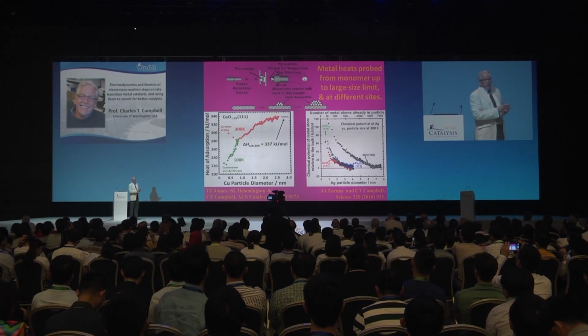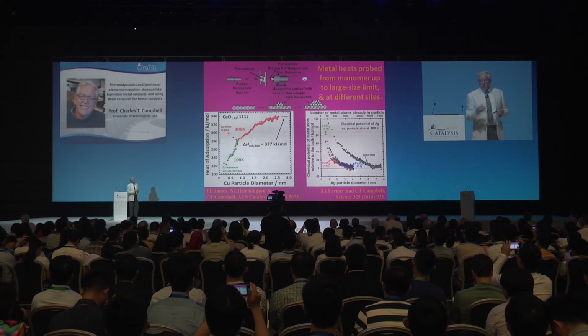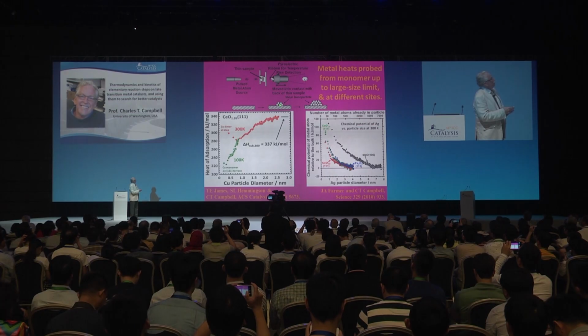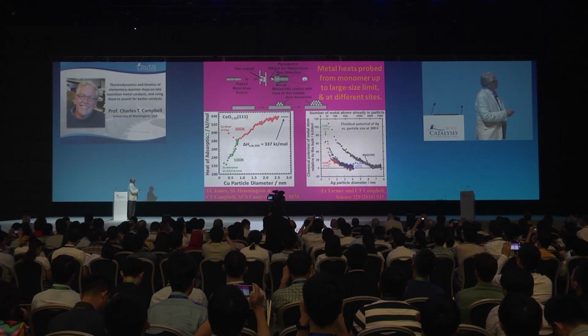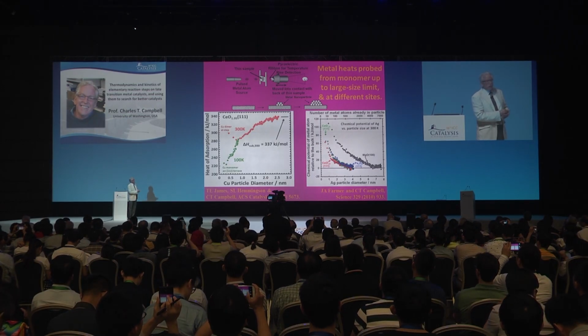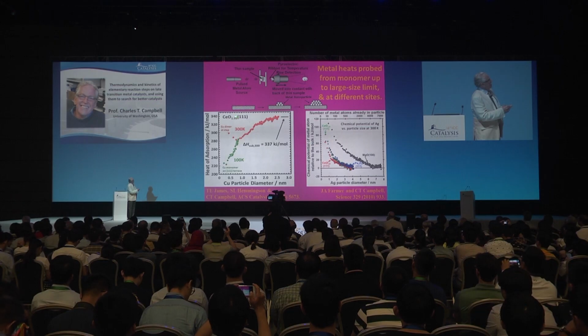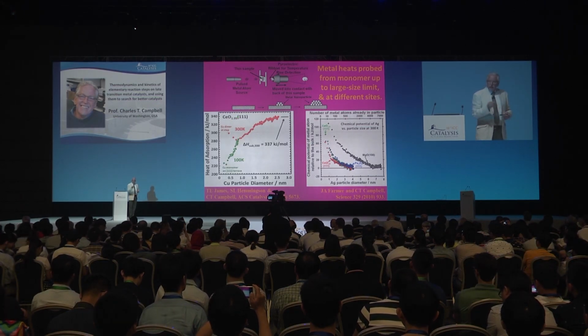And so we're doing experiments where, instead of having a molecular beam of a molecule to do the calorimetry, we have a molecular beam of metal atoms, and we grow nanoparticles and grow those bigger. And so that allows us to measure the heat of adsorption, in this case of copper atoms onto ceria, that's slightly reduced ceria, as a function of the average particle diameter to which that metal atom adds.